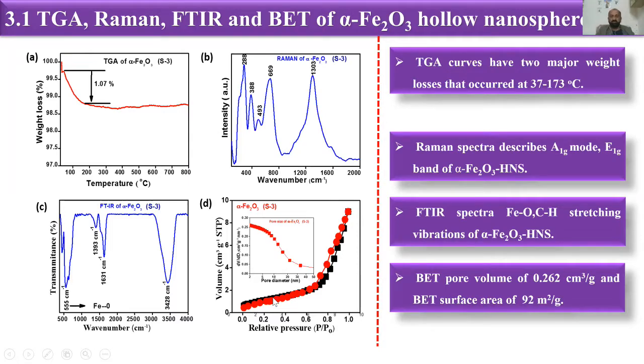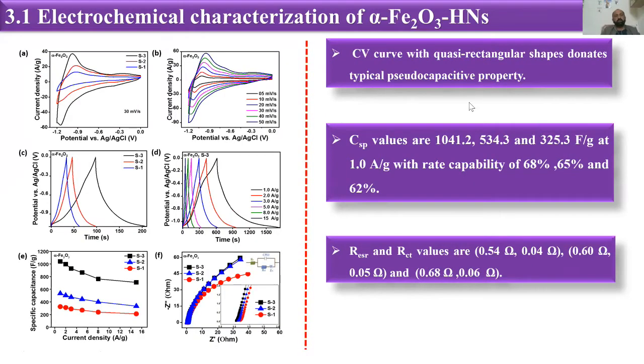We have got the BET spectra for this. Then we have done the electrochemical characterization of our Fe2O3 hollow nanospheres, and we have done the CV for our samples. We have got the pseudo-capacitive property in our CV curves, which are in quasi-rectangular shapes, and we have done it at different scan rates, and then we have got the GCD results for our sample at different scan rates.